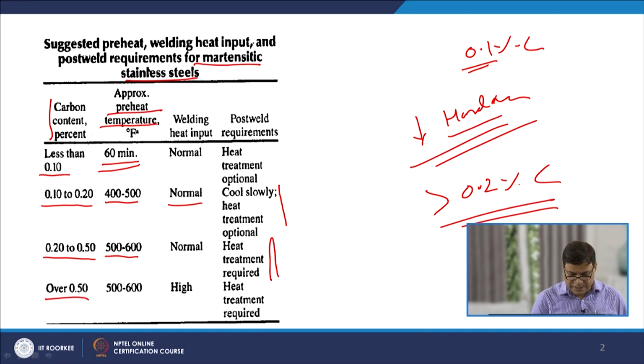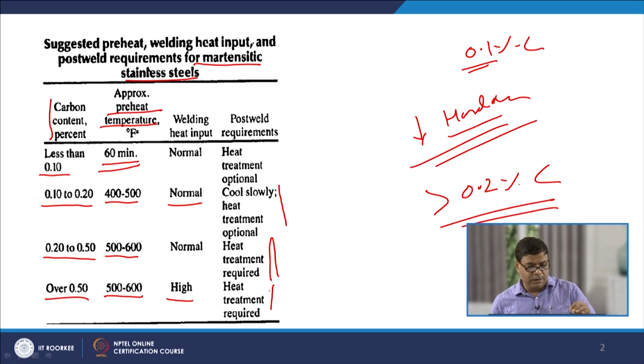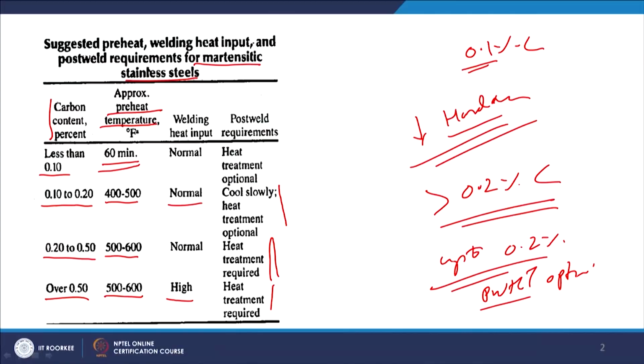Likewise, when the carbon content is greater than 0.5%, then 500 to 600 degree Fahrenheit preheat is used, and especially high heat input is recommended for this case so that the cooling rate can be reduced, and also post weld heat treatment is recommended. So, basically when the carbon content is up to 0.2, then post weld heat treatment is optional, and for a carbon content greater than 0.2% in the martensitic stainless steel, heat treatment is mandatory.